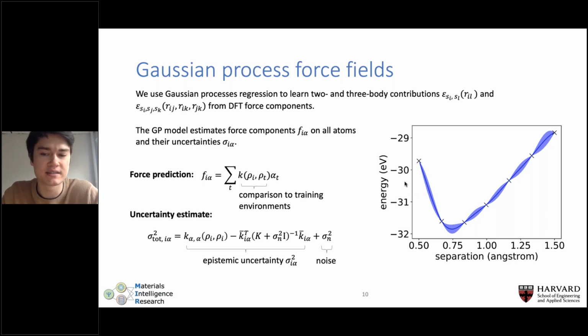Okay, and so this is the nice property of GPs. You have this way of gauging how far away you are from the training data. If you move away from what the GP has been trained on, the error bars tend to increase, if they're calibrated properly. And the way that forces get predicted with the GP is essentially by performing a weighted sum over kernels between the test point, call it the atomic environment ρ_i, and all of the training atomic environments in your training set, ρ_T. And this alpha vector basically comes out of the linear algebra of the GP fit. And so that's how we estimate the mean of the predictive posterior distribution.